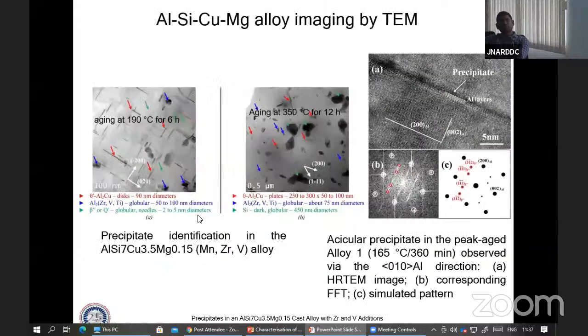And the blue is like a nucleoside, some protein. Suppose you have an aluminum, silicon, copper, magnesium alloy, and you can see some precipitates. Suppose you have done the aging at 190 degrees centigrade for 6 hours, and you have also aged at 350 degrees centigrade for 12 hours. So you can also see the difference or the kinetics of these precipitates under the transmission electron microscope. You can see the red arrows indicate the discs which are 90 nanometer in diameter, and the blue arrows indicate the globular Al3Ti particles or some inclusion. And the green arrows show the needles, those are beta double prime phases.